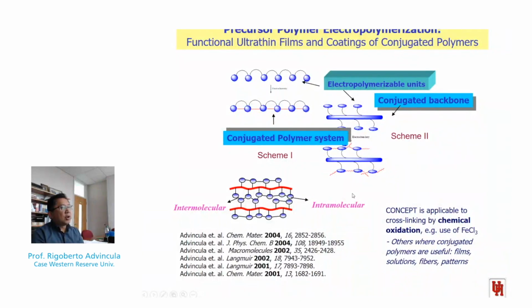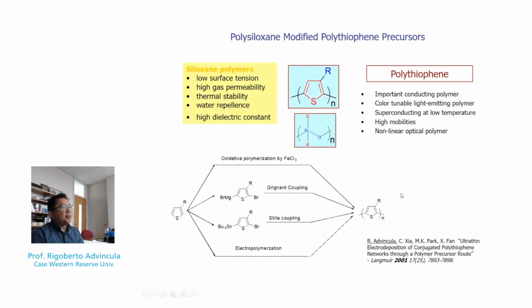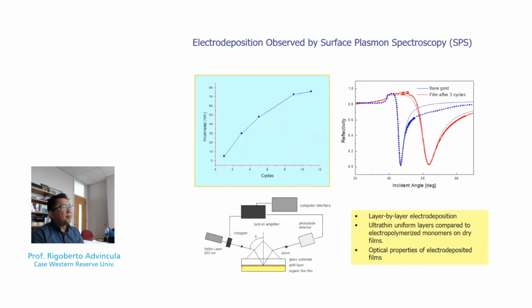substrate surface or working electrode, and we can have essentially a conducting polymer with all its redox behavior and deposition modes. So one of the first papers we published was the electrodeposition of polythiophene. The polythiophene we deposited was uniquely synthesized in that it's actually tethered to a polymer. And polythiophene, of course, can be polymerized with a variety of metal-mediated reactions or oxidative methods. But here, we electropolymerize it using a cyclic voltammetry setup.